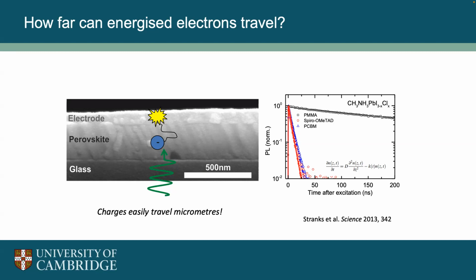So we do an experiment where we put a pulse of light in, and then we look at the light coming out over time. This is in nanoseconds, so it is a very, very fast experiment. Then we do another experiment where we put an electrode on, and we now have an additional boundary condition, where when those electrons hit that interface, they're lost to the system. That means there's a very fast quenching of the emission. So we can model when we have these electrodes.